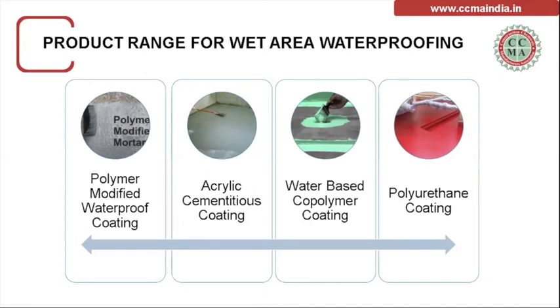No issue. Okay, so as I was mentioning, polymer modified coating is there. Generally, what manufacturers offer and specifiers are specifying in the documents is SBR or acrylic mixed with the cement. Acrylic cementitious coating is well proven and very popular in the industry. It's a pre-packed material with polymer liquid and powder. Then the new technology, which overcomes the shortcomings of acrylic cementitious, is the water-based copolymer coating for high-end structures. Then the polyurethane coatings, available for a long time, a very popular product, single part or two part polyurethanes. Mostly they use 1K polyurethane.